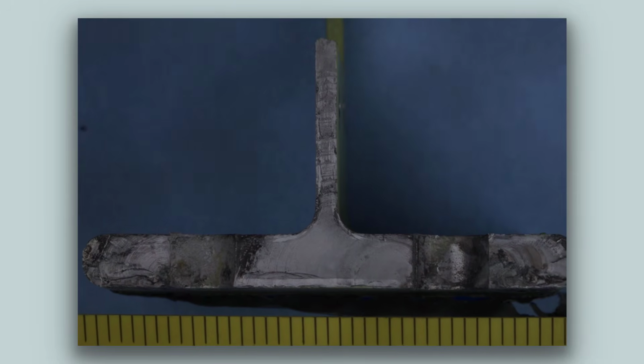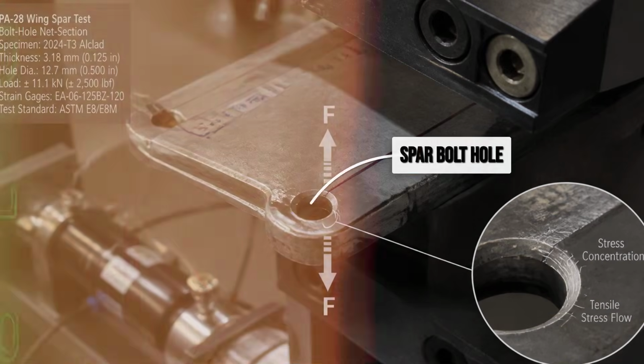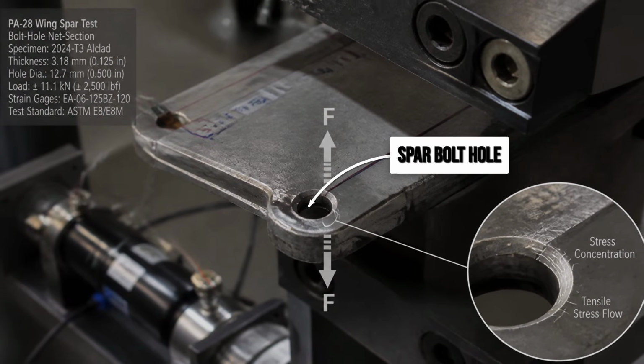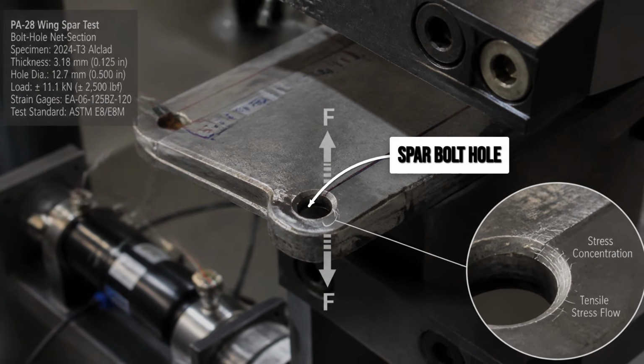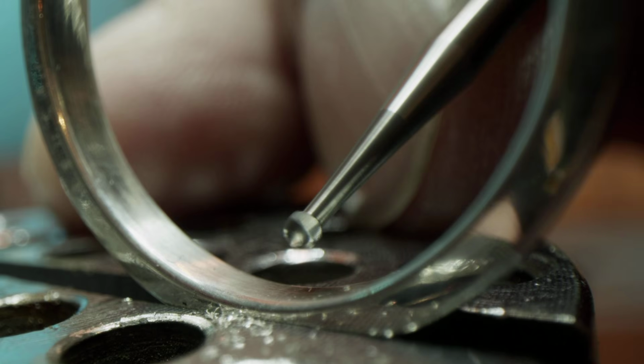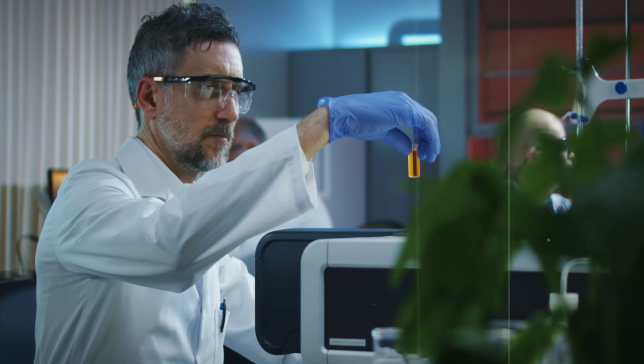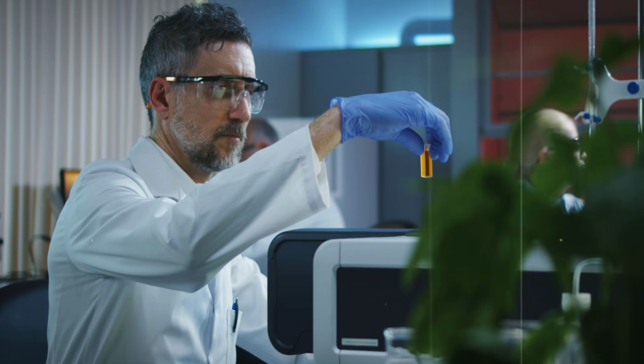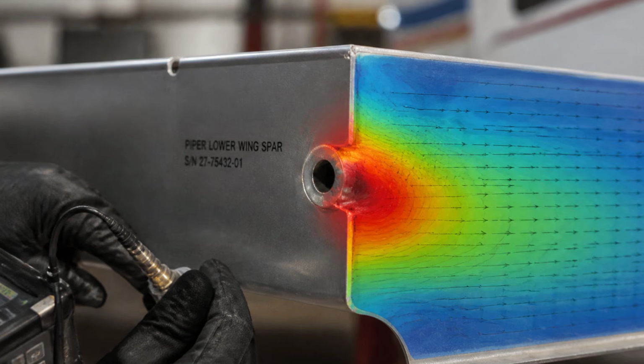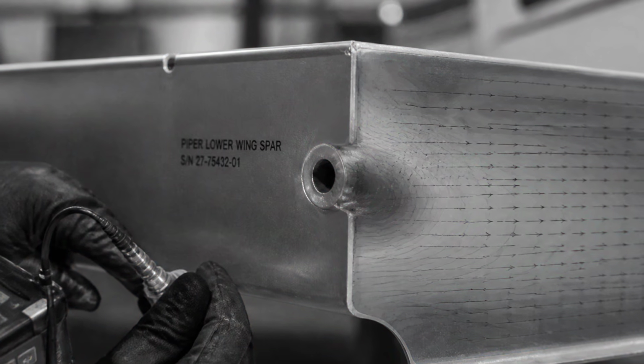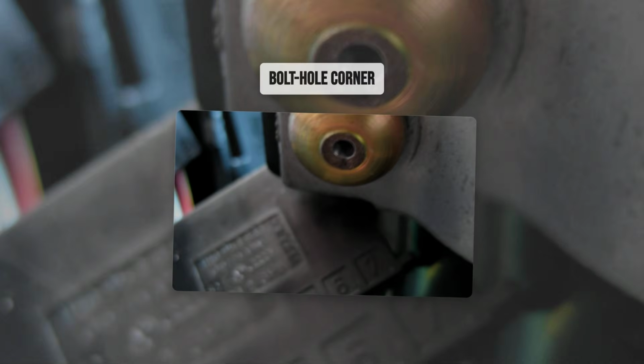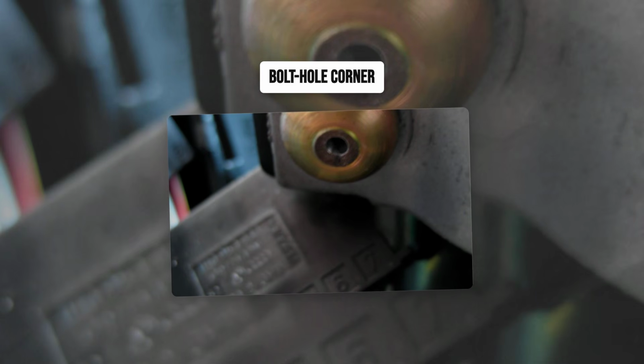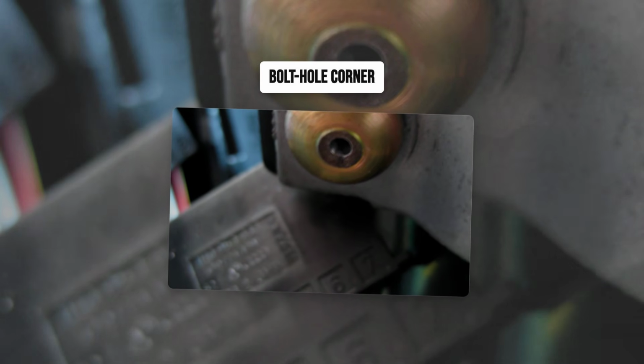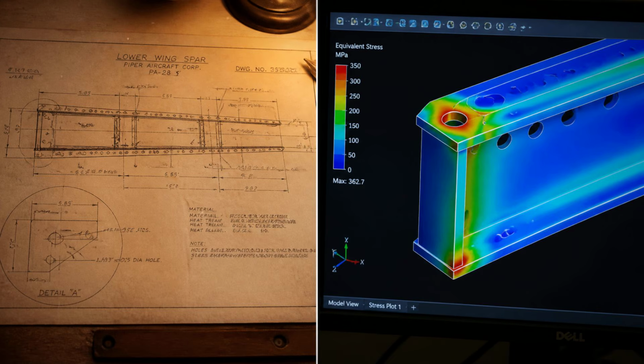Residual tensile stress is a crack's best friend. A fastener hole in a spar under normal flight load already creates a stress concentration. The geometry of a hole in a plate under tension is inherently a high-stress zone. When you add residual tensile stress from the forming process on top of that, the bolt hole corner sees far higher stress during every flight load cycle. Higher than the engineering model predicted when Piper certified the airplane.